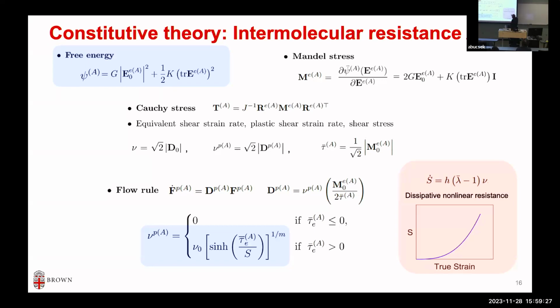The only difference that I want to highlight from what is conventional: a lot of times people do see nonlinear behavior in soft materials, they assume it's rubber elastic. Not all nonlinearity is elastic actually. A lot of it can be viscous. The physics is very different. Elastic will come back, viscous will not come back, right? So putting the wrong idea just because we are used to using the rubber models in the wrong place can sometimes give trouble. So here S is the viscous friction-like behavior. As the chains are aligning and getting past each other, they get more and more friction. So you have a nonlinear dissipative term. So that's your first mechanism.